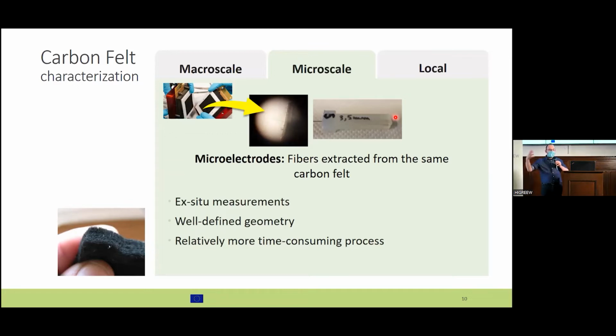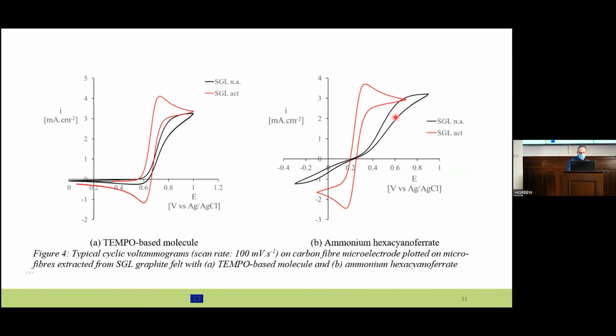When we have a porous electrode, there are different phenomena interplaying, the reactivity and the mass transfer. When we have a single fiber, it is a simpler experiment. We simplify the analysis. Of course, at the end, what is important is to know the activity of the graphite felt, but this allows us to finely tune the analysis in order to be sure that we reach the target of the HIGREEW project.